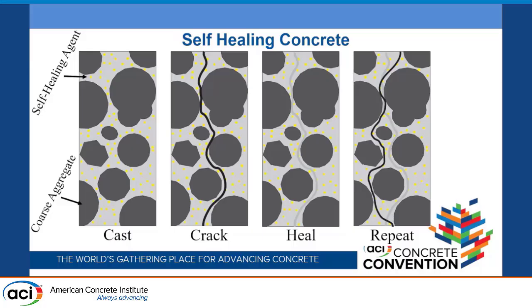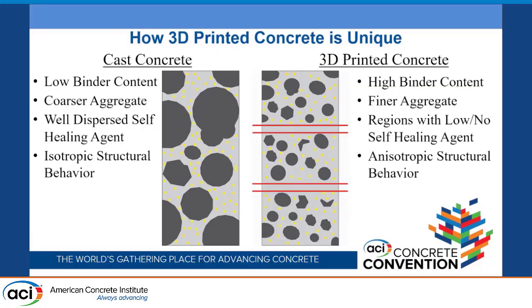Where things get interesting is when we start to look at structures that aren't cast concrete. 3D printed concrete differs a lot structurally from cast concrete, as well as microstructurally. First and foremost, you're going to have a significantly higher binder content. You're going to have a finer aggregate, and you're going to have an anisotropic structural behavior.